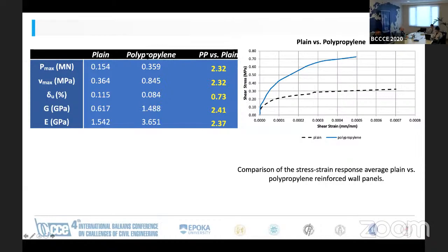If we would compare the mechanical parameters, the maximum load that the plain and the polypropylene panels could carry, there is a clear difference of 2.3 times. So the polypropylene reinforced panel could carry 2.32 times more load, as well as the shear strength. You see for the unreinforced panel it is 0.3 megapascal, and for the reinforced one it is 0.8.